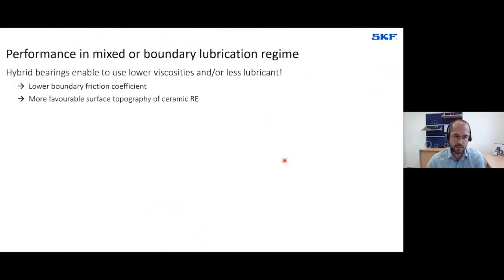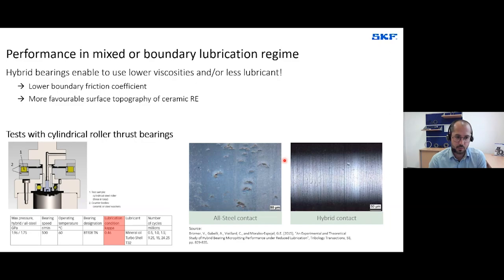But hybrid bearings can cope with those conditions. They are a solution which can cope with those lubrication conditions because they have a lower boundary friction coefficient and a more favorable surface topography of the ceramic rolling elements. Within our SKF research team, we have conducted a lot of different tests for different lubrication conditions, and we have also carried out tests with cylindrical roller thrust bearings and very poor lubrication conditions, so very thin lubricant films.